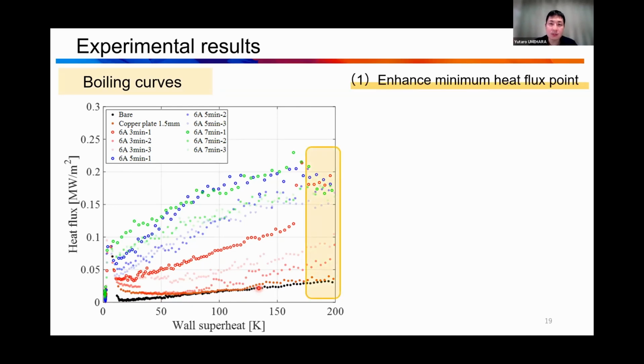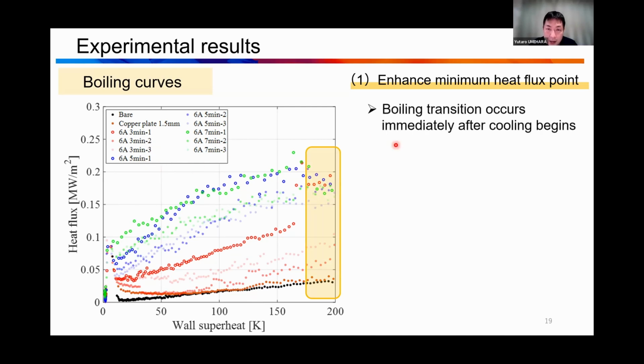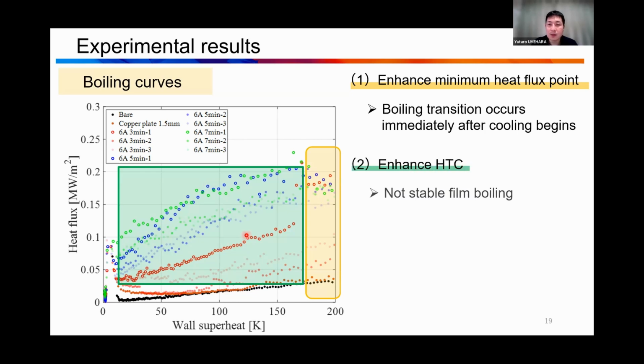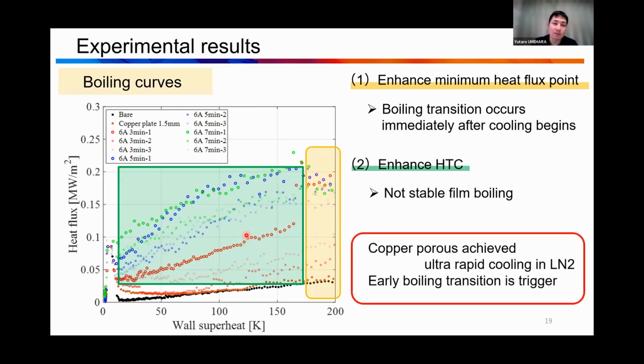But when we immerse the test specimen with copper pores, we can see a high heat flux just at the start, when it was just immersed. Very high heat flux. And the next point is this point, the high wall superheat case. The bare surface has a very low heat flux, but the copper pores case shows very high heat flux. So these two points are very important for reducing the cooling time.